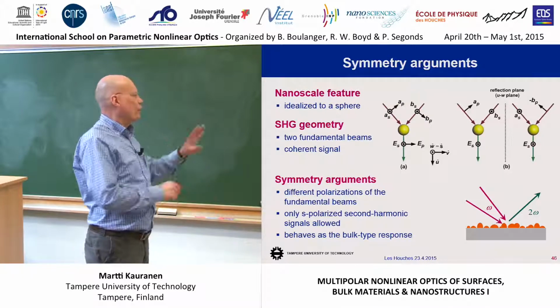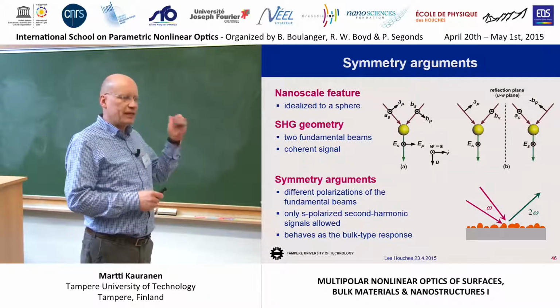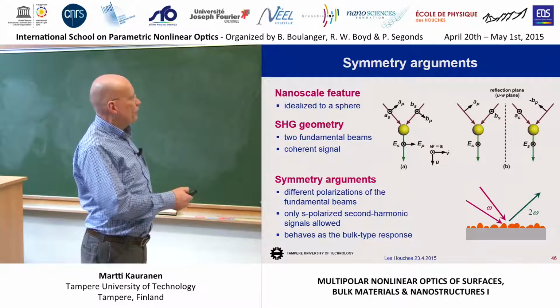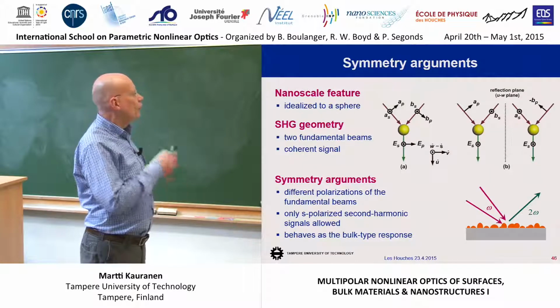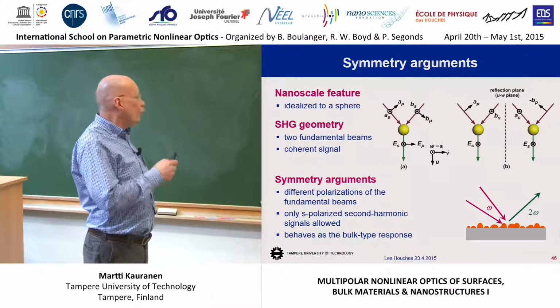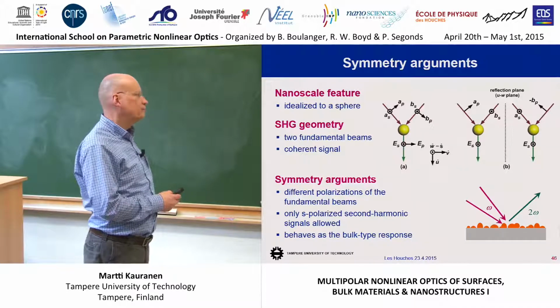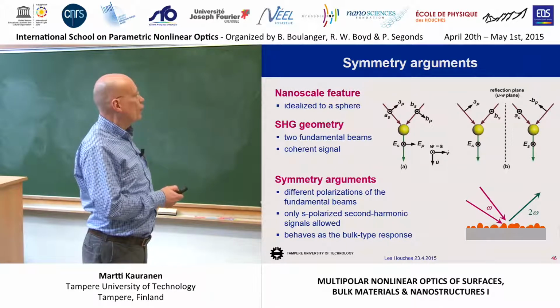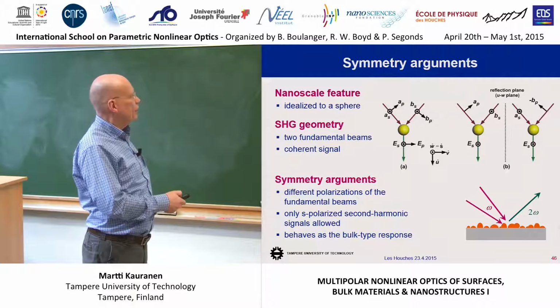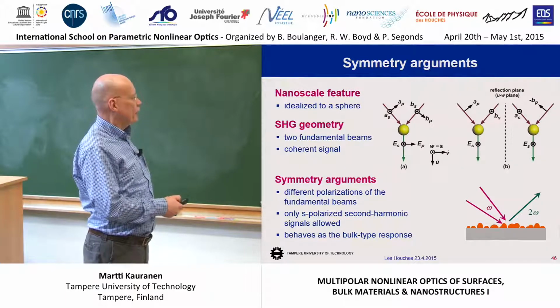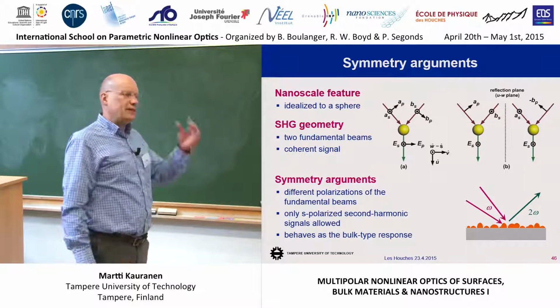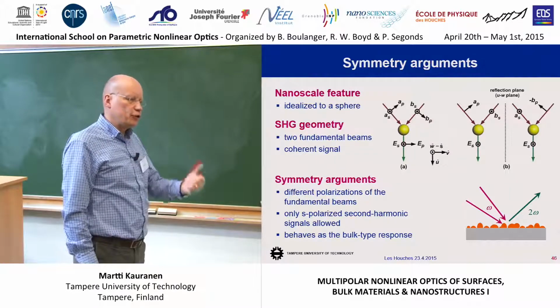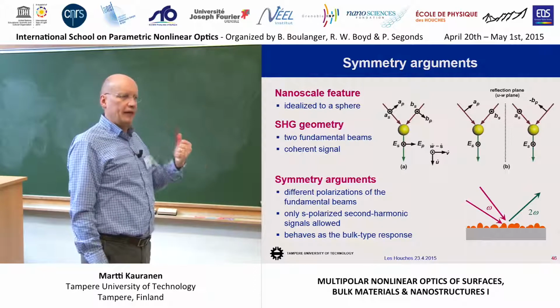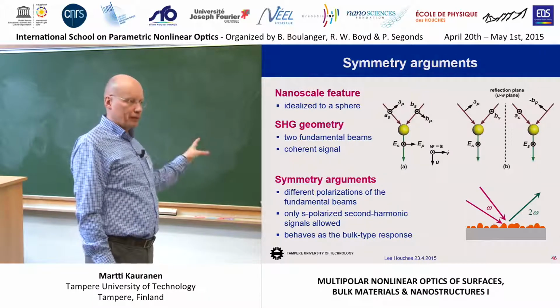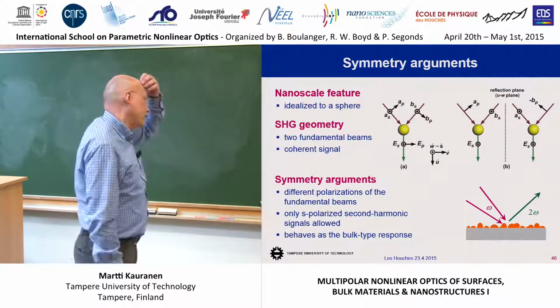When you go through all the possible symmetry operations, not for the sample itself, but for this experimental geometry, you find out that the only signal you can get out of here requires that the two fundamental beams have different polarizations, and then you only get an S-polarized signal. And that is actually exactly the symmetry rules related to this delta prime parameter. So we end up here in a funny regime.